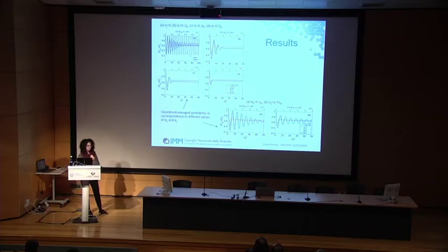This approach is valid whatever the physical system is. Once we have specified this value of J0, we can have a physical time in seconds, for example. In fact, I have put another horizontal x-axis in the upper part of all these plots, in which I fixed J0 equal to 1 microelectron volt. That is a typical value for the qubit systems that we study in silicon. And as you can see, here we can have an estimation in seconds of the dephasing time of the disorder average probability.